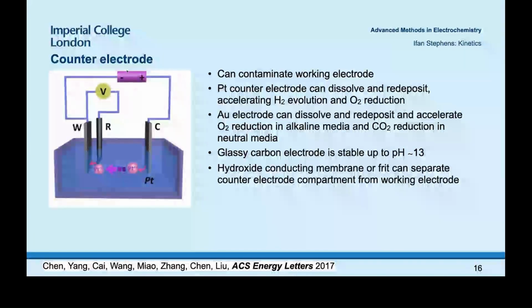But even a platinum counter electrode, while generally quite stable, can dissolve somewhat and redeposit at the working electrode. Imagine you are looking at a relatively inactive catalyst for hydrogen evolution. If you accidentally deposit even small amounts of platinum, you can make the catalyst look a lot better than it really is. So contaminants of platinum can be really counterproductive.